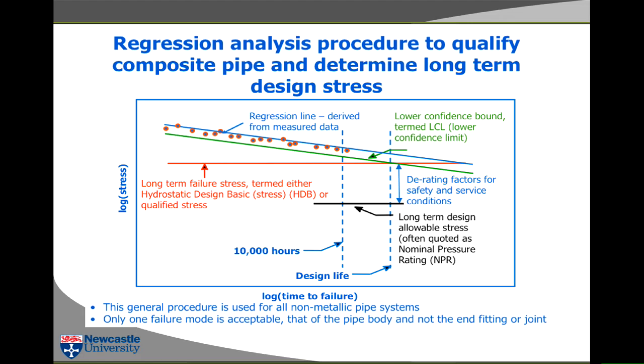And in fact, the lower confidence limit, if you remember, the thing that we usually plot is the 95% confidence limit. Do you remember that? It's 2 standard deviations. Remember, 2 standard deviations from the line gives you 95%. If you haven't done that, or you don't remember it, write it down now. So your lower confidence limit is just the line minus 2 standard deviations.